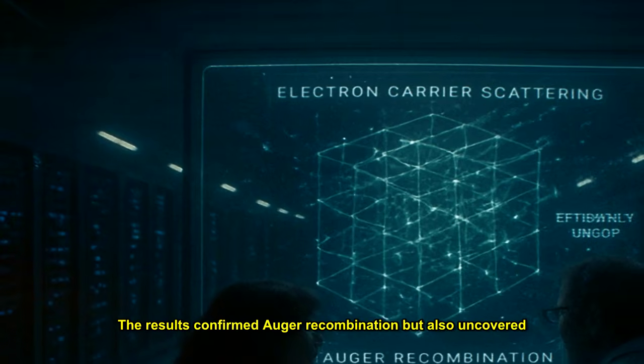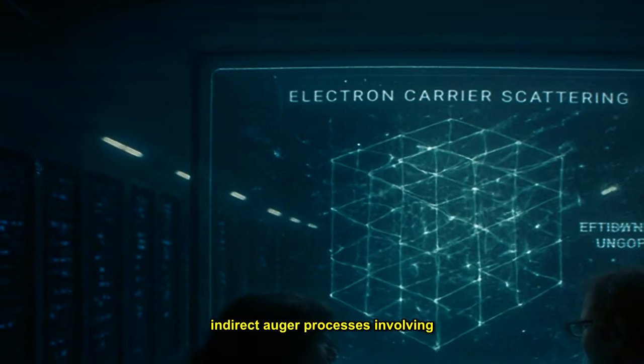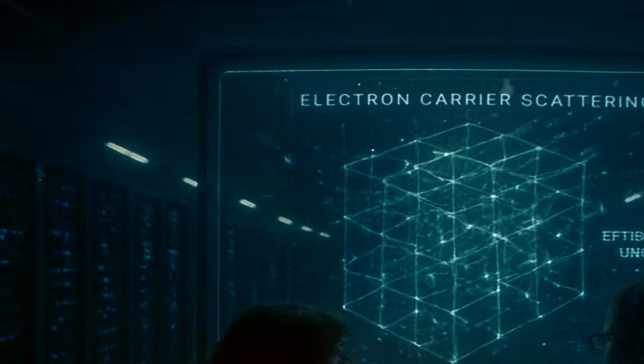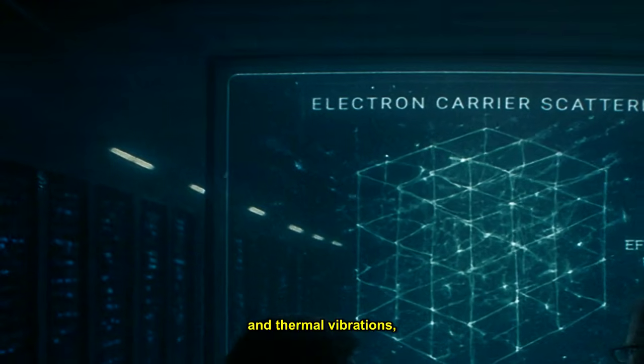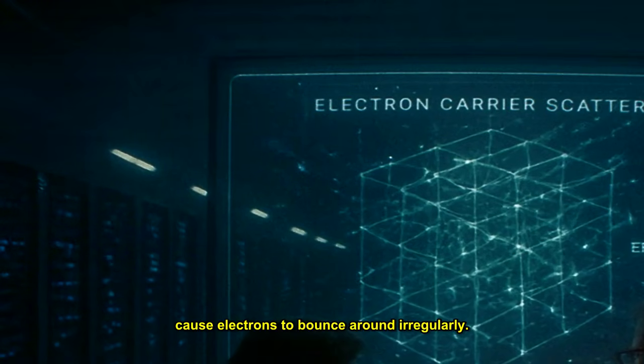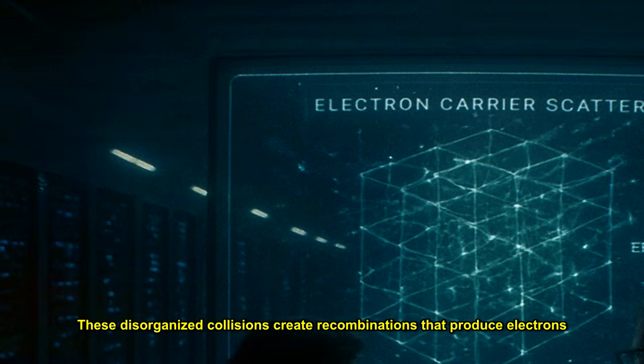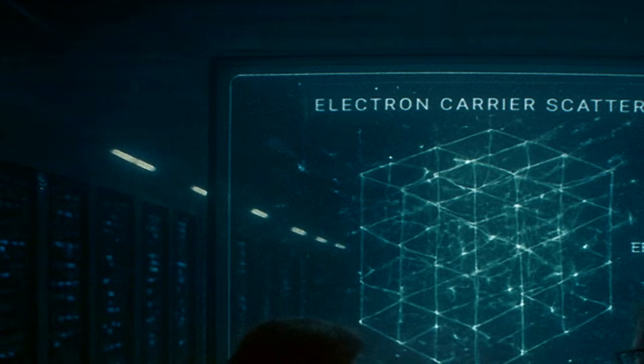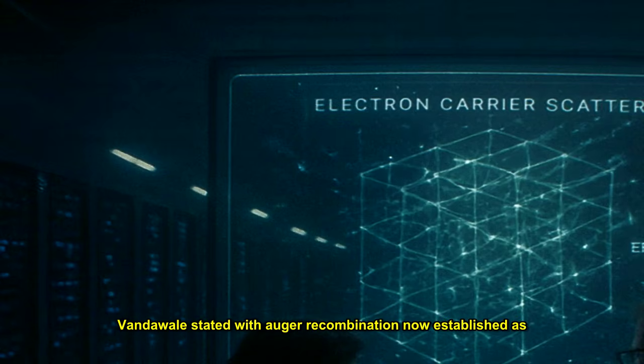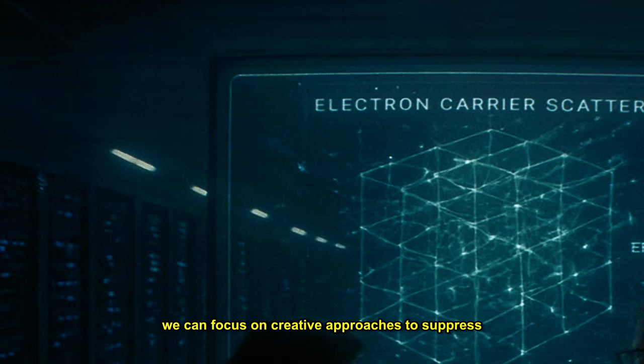The results confirmed Auger recombination, but also uncovered indirect Auger processes involving carrier scattering. Imperfections in the gallium nitride crystal lattice and thermal vibrations cause electrons to bounce around irregularly. These disorganized collisions create recombinations that produce electrons or holes instead of photons. The energy dissipates as heat. The effects of indirect Auger recombination were found to be about 1,000 times stronger than direct Auger processes. Van de Walle stated, "With Auger recombination now established as the culprit, we can focus on creative approaches to suppress or circumvent this loss mechanism."